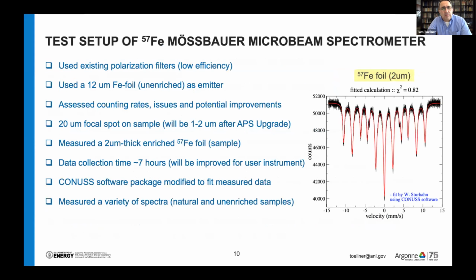So here's a measurement of the test setup. I used some existing polarization filters. One of them was low efficiency. The other one was a recent modification that I introduced a couple of years ago. And then the emitter was just an unenriched iron foil mounted on a velocity drive with a small magnetic field so that it was magnetized. I did this to assess the counting rates and issues and all the things that I could do to improve it. And the spot size in this case was just 20 microns.